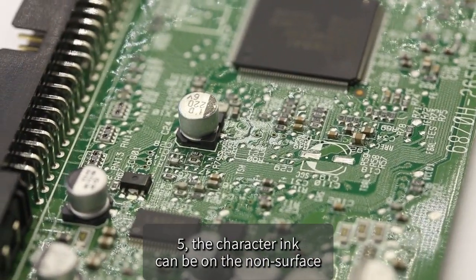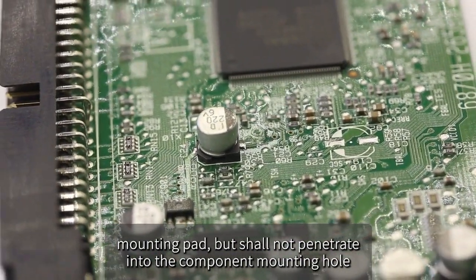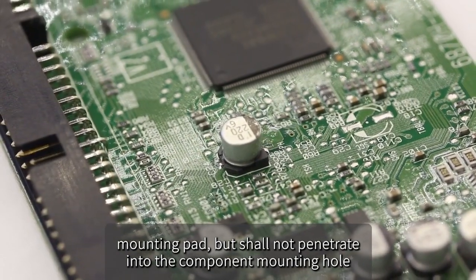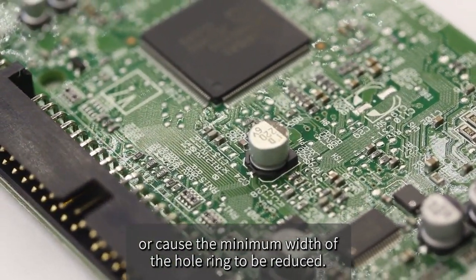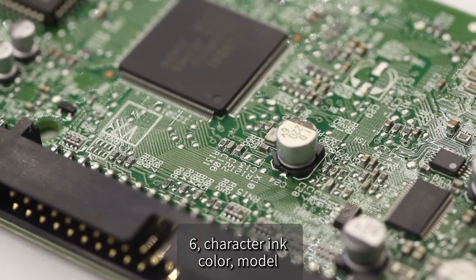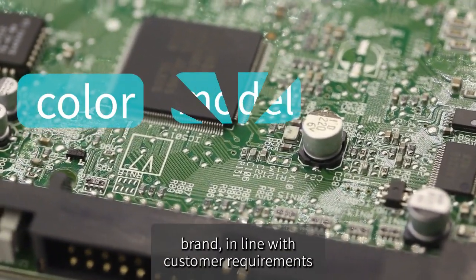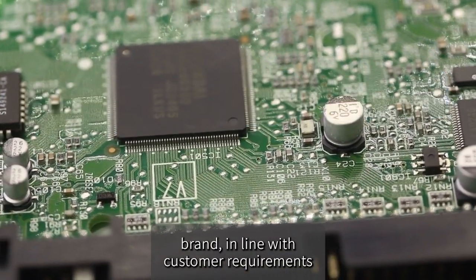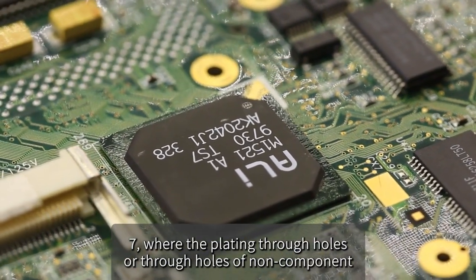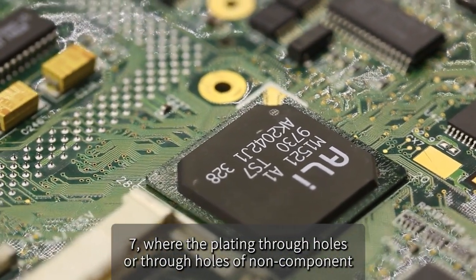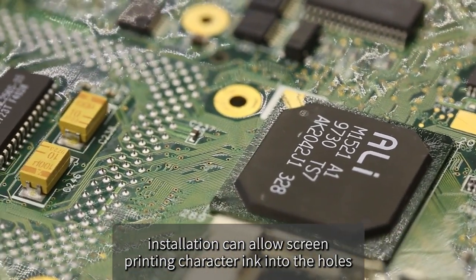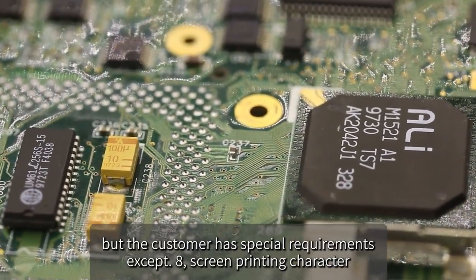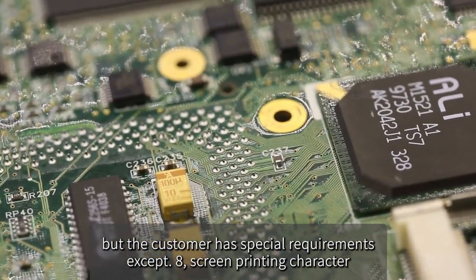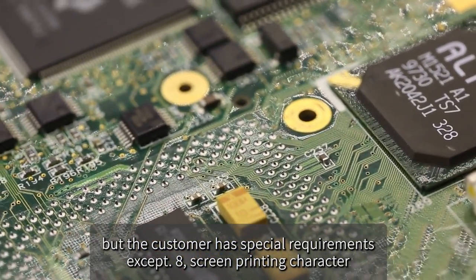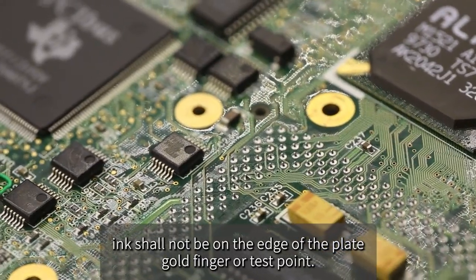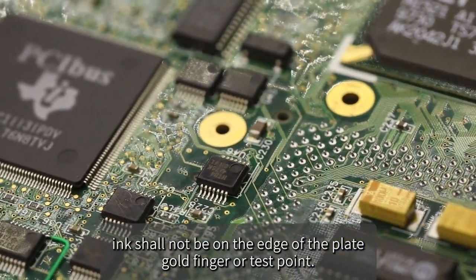The character ink can be on the non-surface mounting pad, but shall not penetrate into the component mounting hole, or cause the minimum width of the annular ring to be reduced. 6. Character ink color, model, brand, in line with customer requirements. 7. Plated through holes or through holes for non-component installation can allow screen printing character ink into the holes, except where the customer has special requirements. 8. Screen printing character ink shall not be on the edge of the plate, gold finger, or test point.